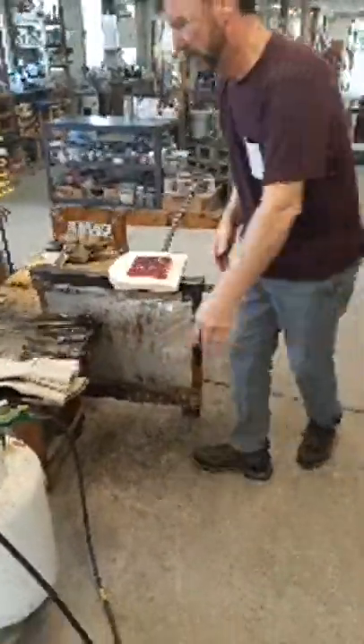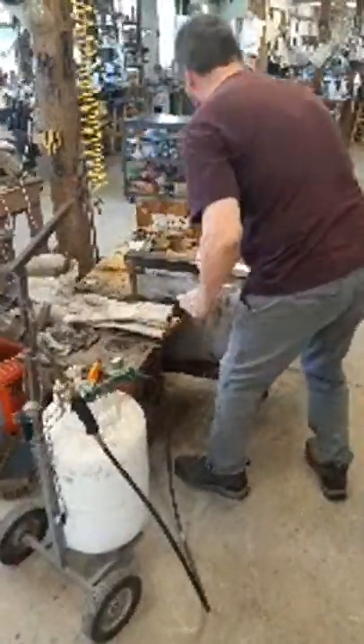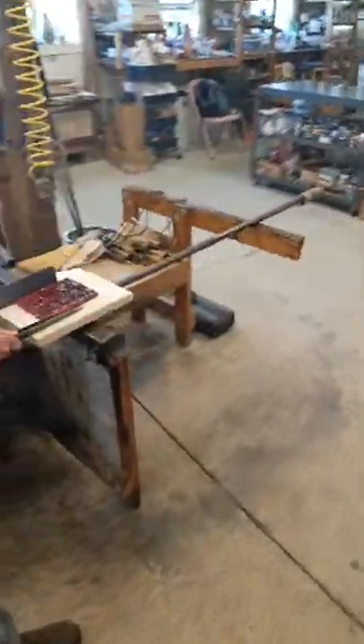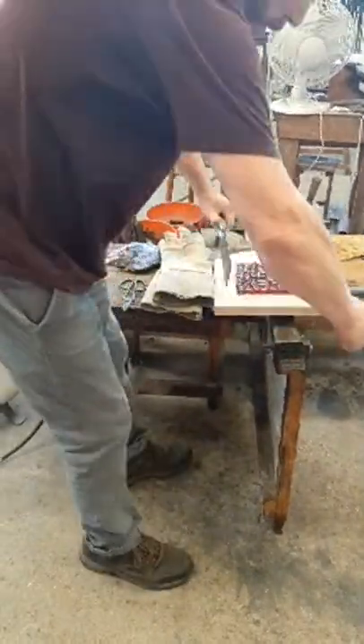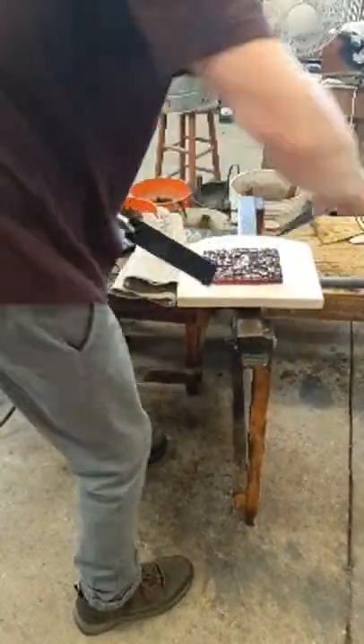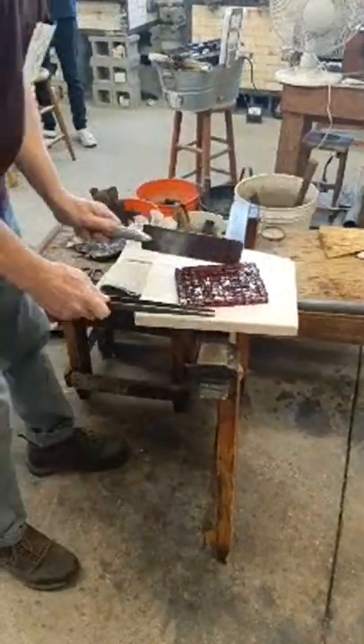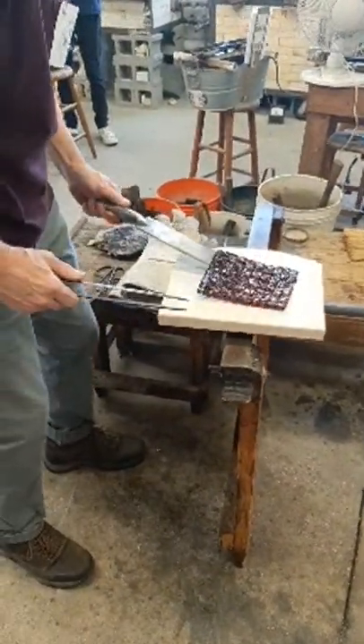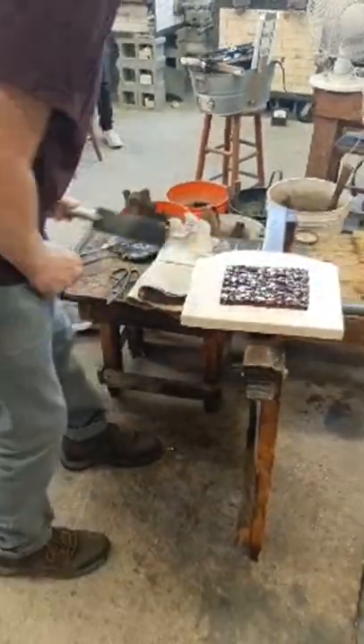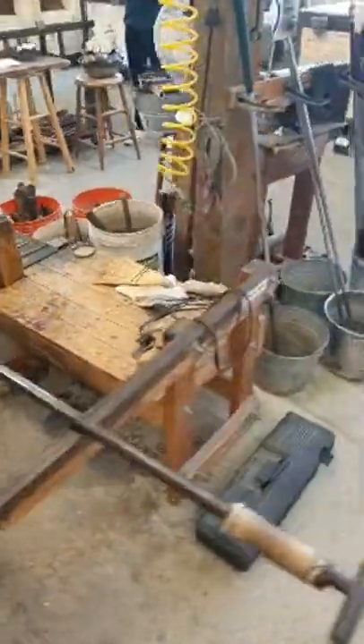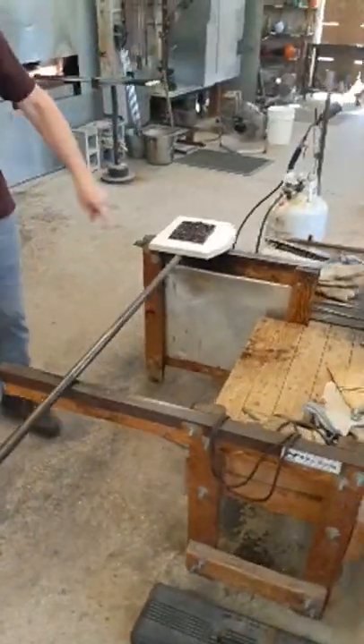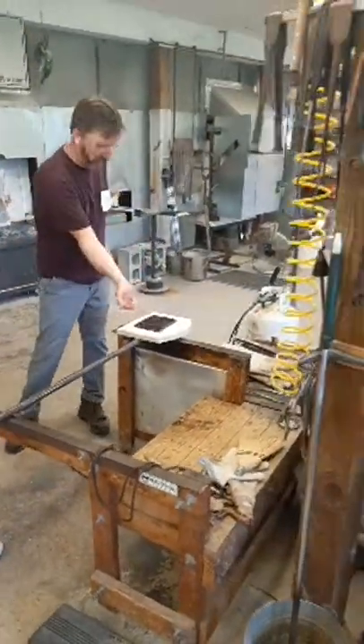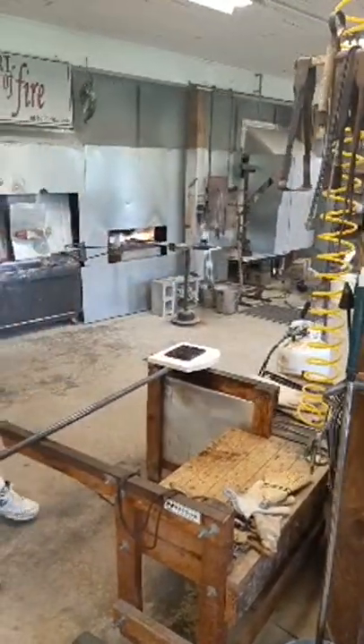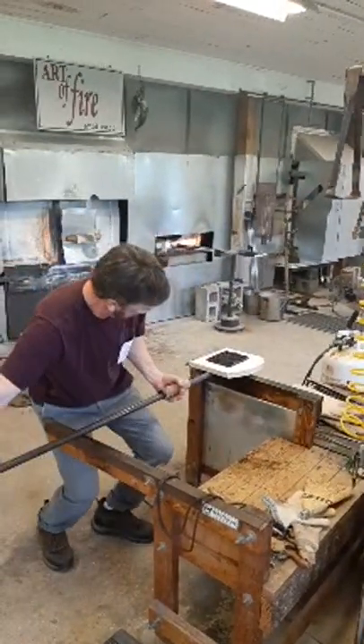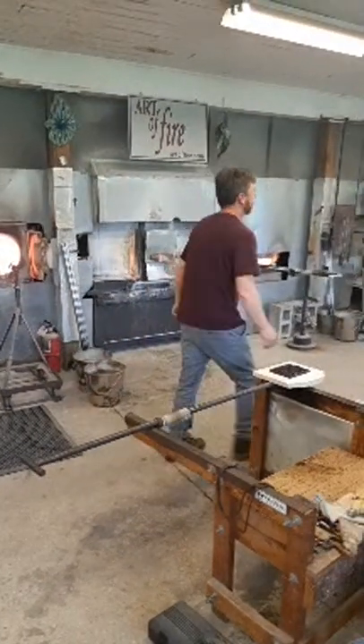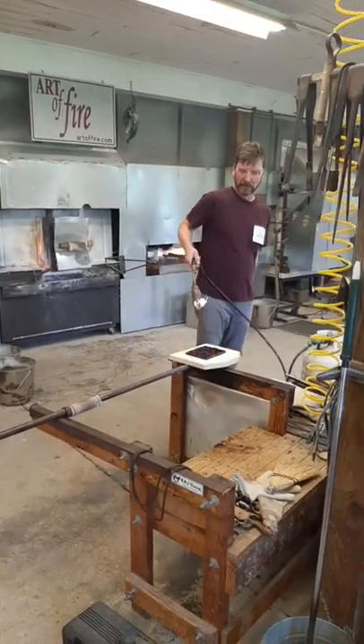Now you see where the orange glow is around the perimeter. And this will tell us whether it's fused. Now he's squeezing it together now, forcing it between the two tools. And if it's fused, he can lift the edge and it's pretty much sticking together as he turns it around. There you go. So now he's getting his fusing. So he didn't have to go really hot with that. He didn't have to go to 1800. Okay? So he had the murrini preheated, got them all fused together. He's letting Foster know what it is he wants done with it. Torch in the middle.